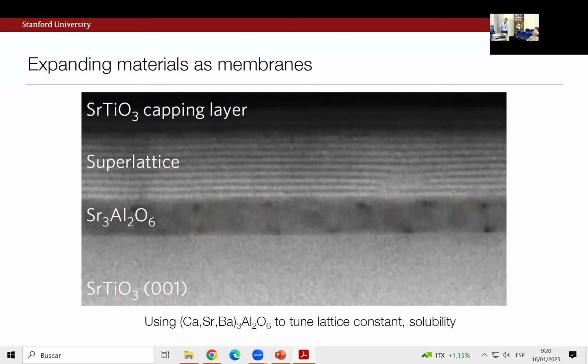And so maybe, or at least my naive understanding, is that this system is a kind of lower density, right? There are these vacancies compared to the perovskite nearby. And so energetically, it's often preferable for dislocations to go in this system. And so just phenomenologically, we find that within a certain percent lattice mismatch, things go very nicely. We can release large area membranes. But if you go beyond that, I think many of you have experienced, if you're playing with these things, lots of fracture and cracks, right? To small pieces. And so this is motivating our use of this tuning of the lattice constant of the soluble buffer layer to accommodate that.